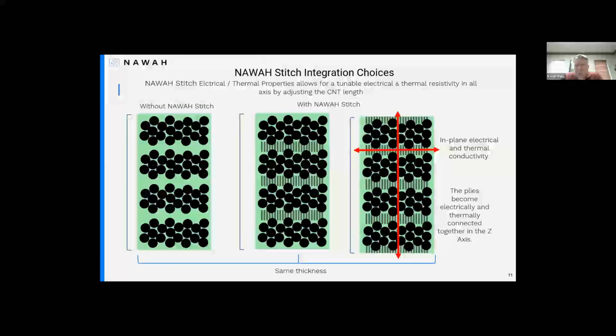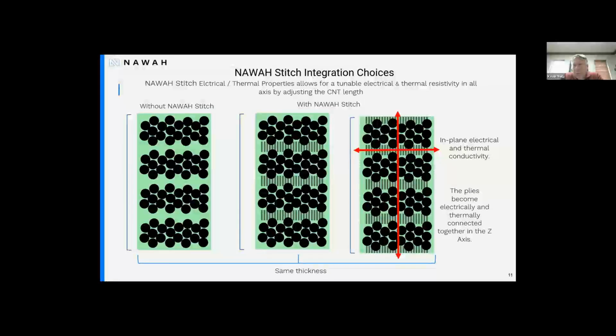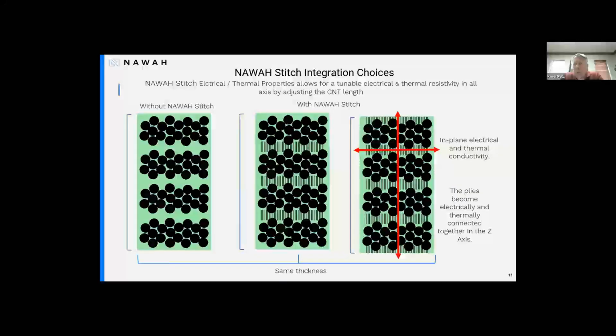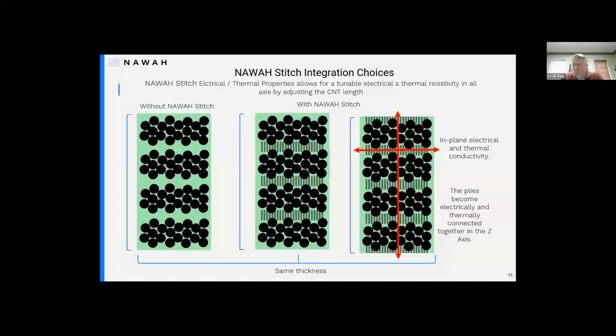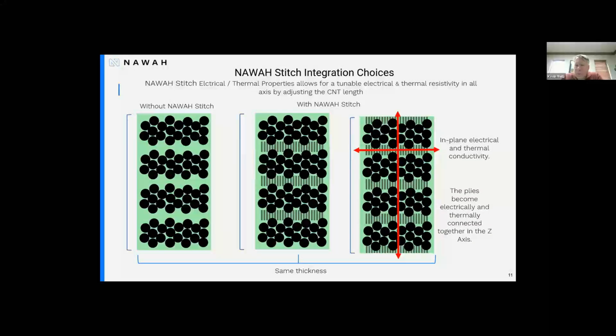With this approach, you can change where you put the material in a layup, because what we do is transfer the carbon nanotubes into a prepreg, a resin film, or a veil cloth, and then the customer can apply it where he needs it. But what the carbon nanotubes do is increase the electrical and the thermal conductivity in the X, Y, and the Z direction. So we're giving you thermal and electrical conductivity throughout the composite panel, giving you the ability to have a multifunctional structure.